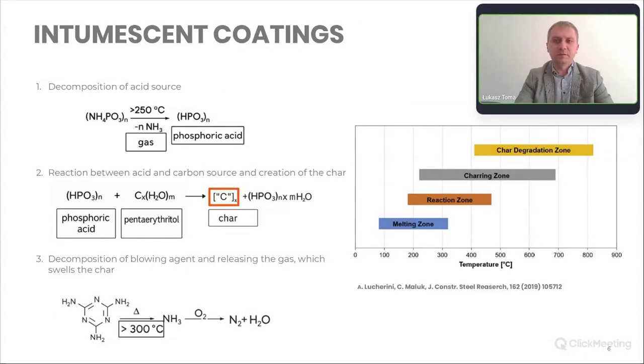I mentioned the intumescent coatings, which are very important in case of hydrocarbon fire protection systems. So what is this kind of coating? The main role of intumescent coatings is creation of a protective layer of char during the fire, which can act as a kind of insulation that reduces heat transfer between the fire and the substrate. To create such a layer, we need three key components.